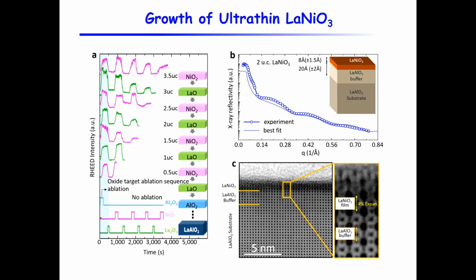We did the cross-section TEM. We can count the atoms, and these are the 2 unit cell layers, and it does look like 2 unit cell, or maybe a little bit more, but it's 2 unit cells. And we do see the buffer layers, and we also can see that the lattice expands somewhat, which is consistent with what we would expect.